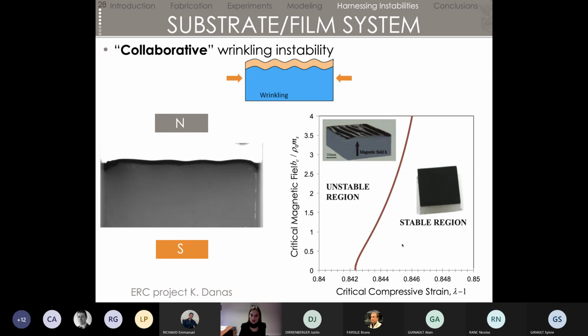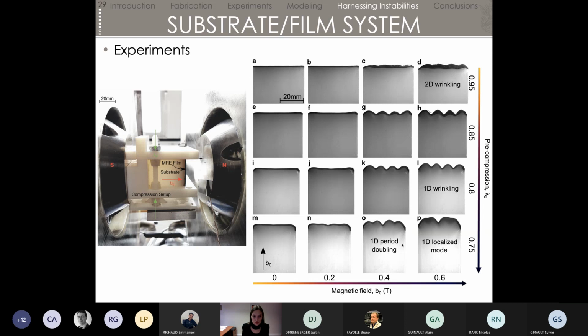So you can see here on the graph, at the bottom, it's the compressive strain you would need to go from stable to unstable. And so the idea is that you can compress a little bit less, but then switch on the magnetic field to go inside the unstable region. So we did some experiments to prove that. So we have a simple casing that applies a finite compression on our system of substrate and MRE film, and then we apply the magnetic field.